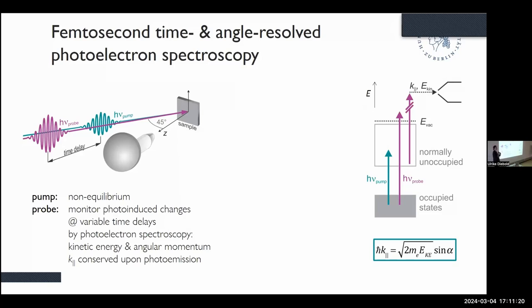And by this, depending on the choice of the photon energy that we use, we can either look at population dynamics and normally unoccupied states, or at changes of the occupied electronic structure, like the whole manifold of electrons. And this depends on the photon energy that we use for probing those photoelectrons. We do this not only energy resolved, but also we resolve the momentum parallel to the surface. So we learn something about the degree of localization of the electrons.